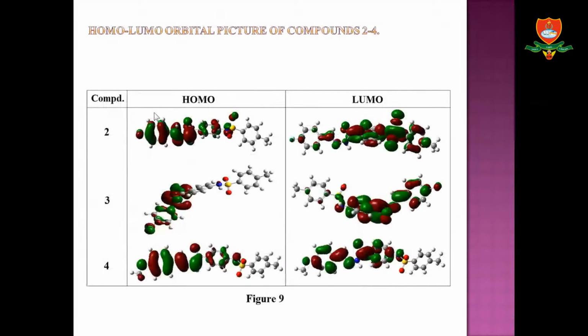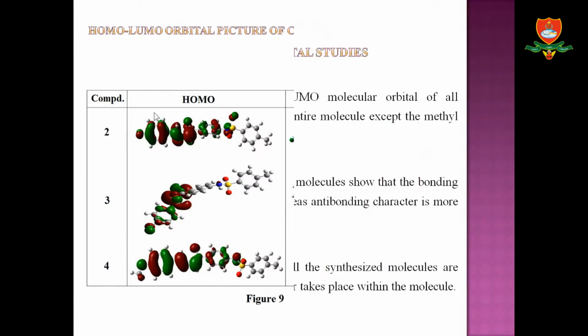This figure shows the HOMO-LUMO orbital picture of compounds 2 to 4. So we optimize the structure using the DFT B3LYP method with 6-31G(d,p) as the basis set. And then once we obtain the optimized structure, we perform the HOMO-LUMO orbital analysis for these compounds.